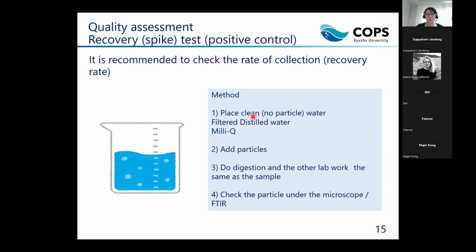So the method is almost the same as the blank test. But the difference is you need to add some particles to check the recovery rate. And after collecting the sample, you should check the number of particles you could collect and check the recovery rate.